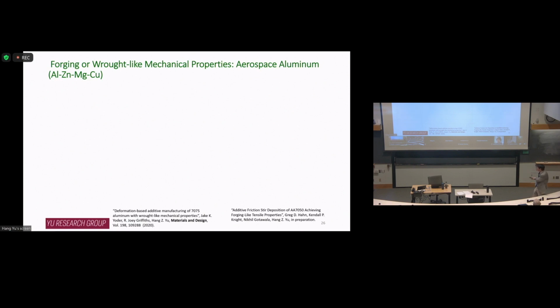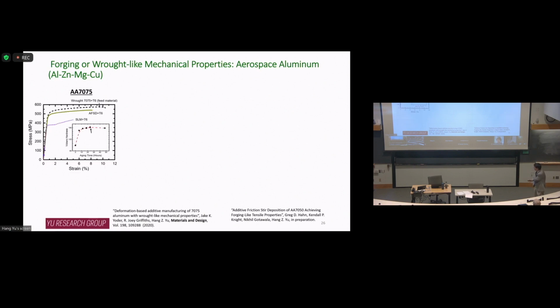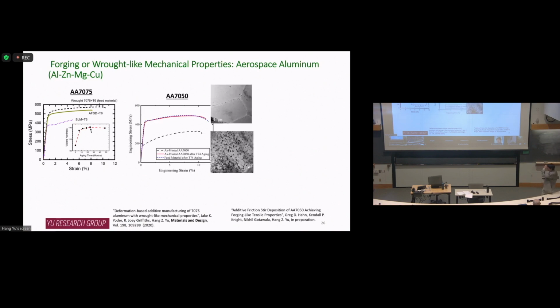But for us, things are much easier, right? We just use an engineered alloy as our feed material, our deposit material. Fully dense, and then we do a solution treatment and aging. We get the right temper. We do tension testing, and we can get comparable mechanical properties to a forging bar or rod material. Another example is very similar but with a slightly different composition, 7050.